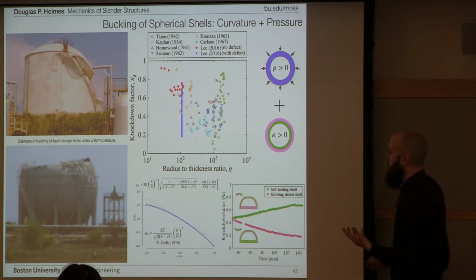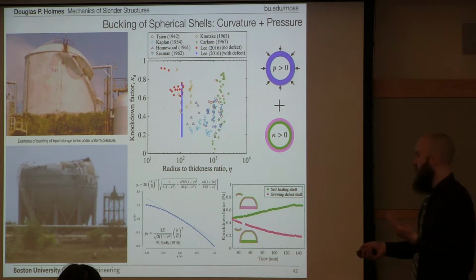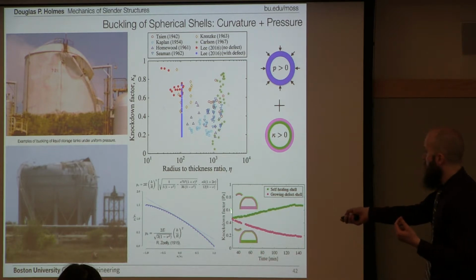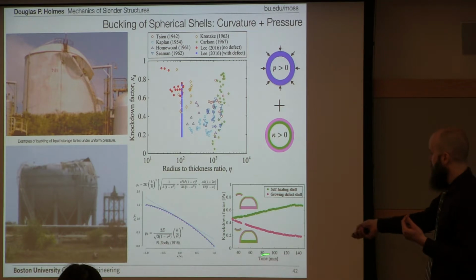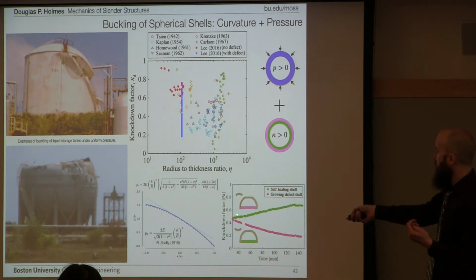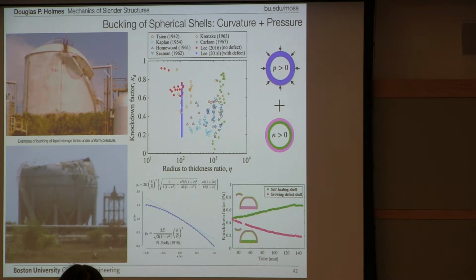We've done some preliminary experiments that show this in fact actually works. So you can measure this knockdown factor very, very precisely as a function of time, which is a stand-in for curvature here. And we show that if we turn up the pressure, the knockdown factor goes down. If we turn up the curvature, the knockdown factor goes down. If we turn down the curvature, the knockdown factor goes up. And so we're starting to make self-healing shells.